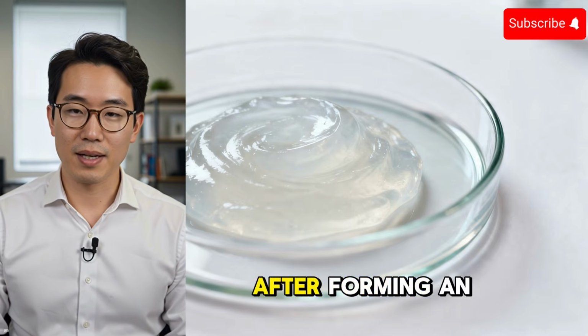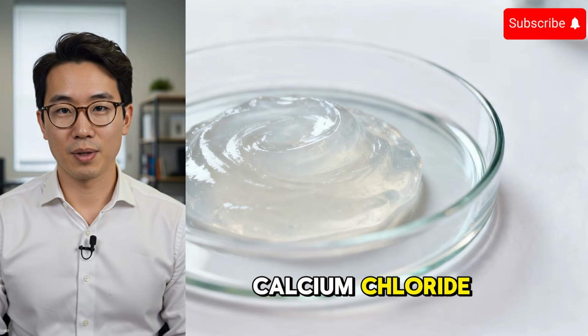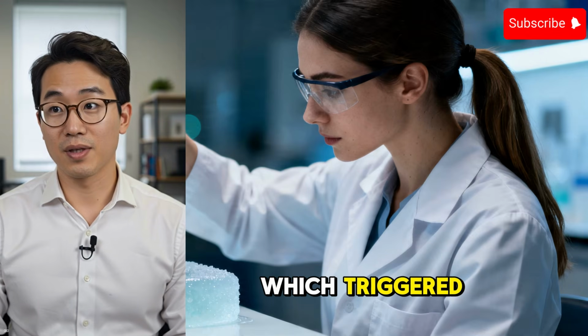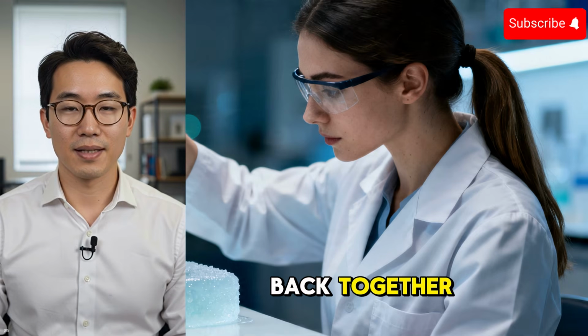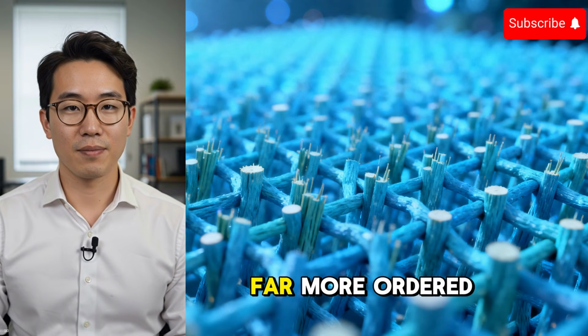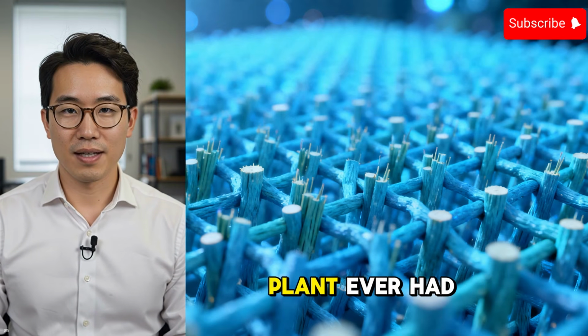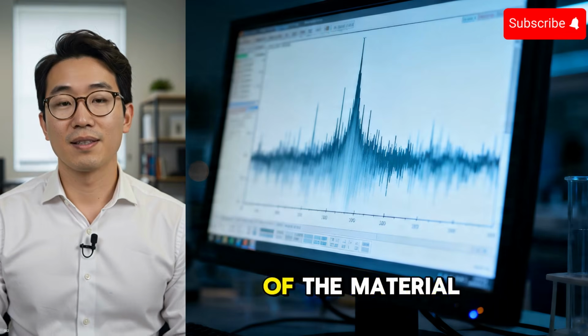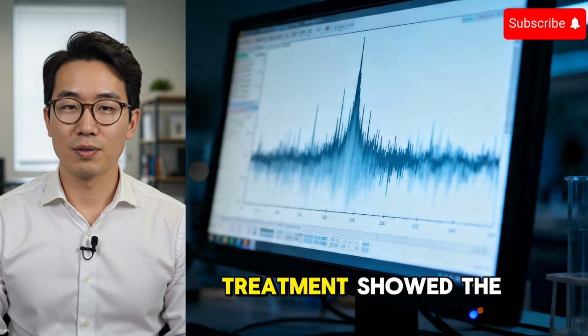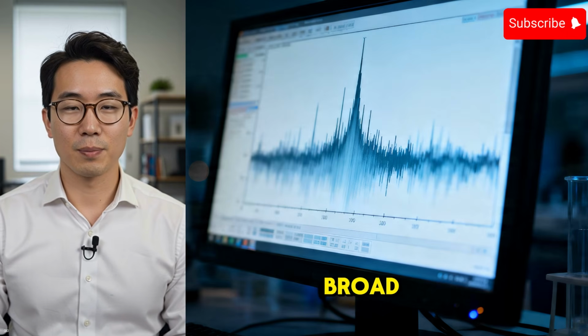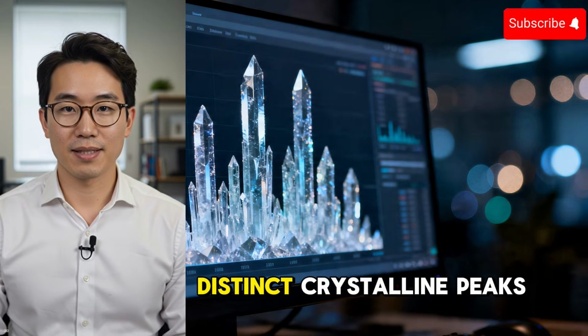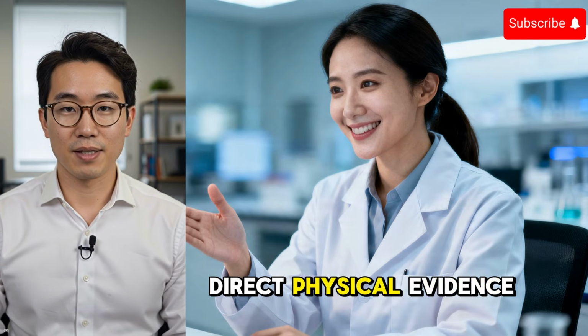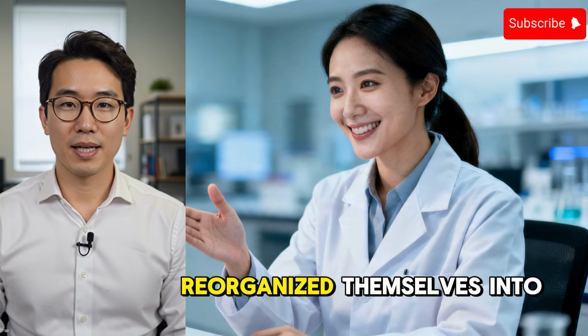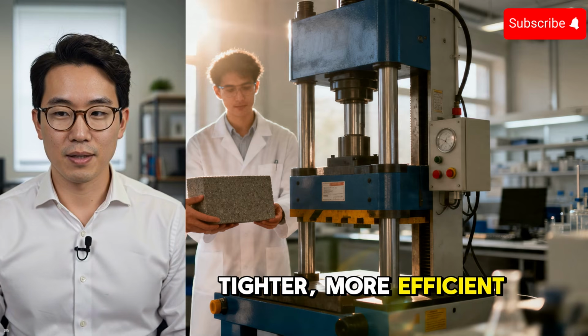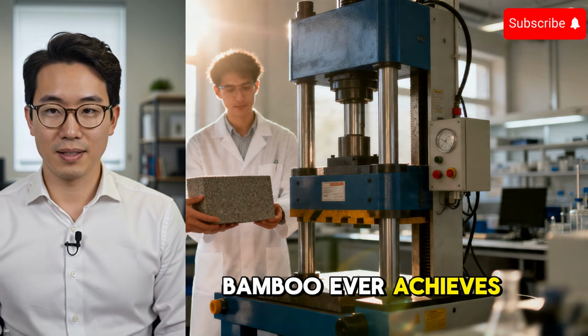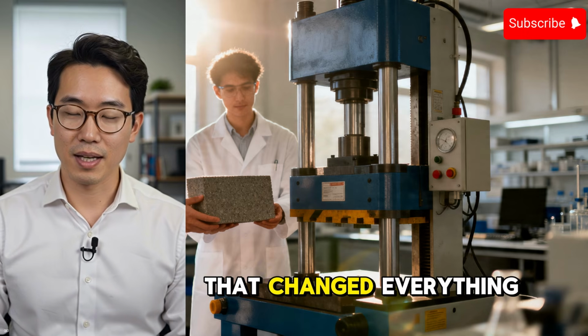It did. After forming an intermediate gel using calcium chloride, the team treated it with ethanol, which triggered the cellulose chains to snap back together, this time forming far denser, far more ordered hydrogen bonds than the original plant ever had. X-ray analysis of the material before and after this ethanol treatment showed the structure shifting from a broad, disordered pattern into sharp, distinct crystalline peaks. Direct physical evidence that the cellulose chains had reorganized themselves into a tighter, more efficient arrangement than raw bamboo ever achieves naturally. Here's the part that changed everything.